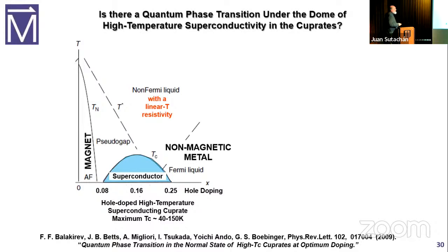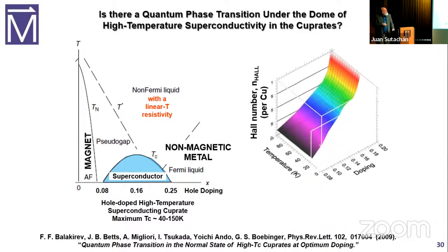So in the mid-90s, I started applying high magnetic fields to high temperature superconductors to peek behind the curtain, because high magnetic fields destroy superconductivity. You remember the slides before. The spins line up. So this is the gentlest way with high temperature superconductors to remove the superconducting phase, and the idea is to see, is there a quantum phase transition under the dome of these best of the high temperature superconductors. So we measured the number of carriers in the material as we changed the doping. So here, if you just look at 0 temperature, you can't take any data because it's superconducting.